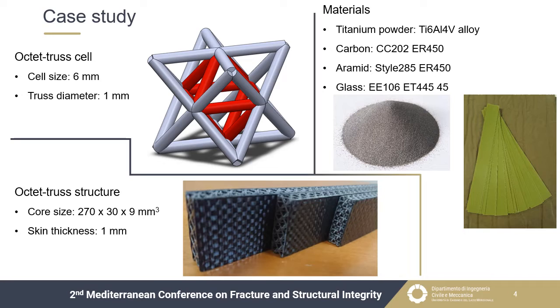The produced lattice core had a section of 30 mm by 9 mm and a length of 270 mm, while the skin thickness was equal to 1 mm for all types of material considered. The titanium powder adopted in the present research activity was made of the Ti6Al4V alloy, that is the most used titanium alloy in the aerospace and aeronautical fields. As concerns the skins, three different types of fiber were taken into consideration: carbon, aramid, and glass fibers. All the prepreg had an epoxy resin as matrix, and a satin weave fabric as reinforcement, except the carbon one that was plain weave.